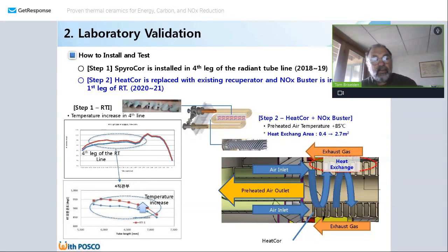So they really moved in two steps. The first step was to apply the SpyroCor technology that was earlier introduced, and then following the SpyroCor technology, apply the HeatCor technology to replace the existing recuperator. And then finally from this, because they did, as Brad showed, increase NOx, we installed the NOx buster technology in the system. So looking at graph 1, SpyroCor produced an increase in the temperature of the radiant tube, which we expect. This allows more energy to be transferred into the furnace, limiting the amount of energy going out the exhaust. When we look at graph 2, taking a closer look at the fourth leg temperature, a 25 degrees C increase is observed.